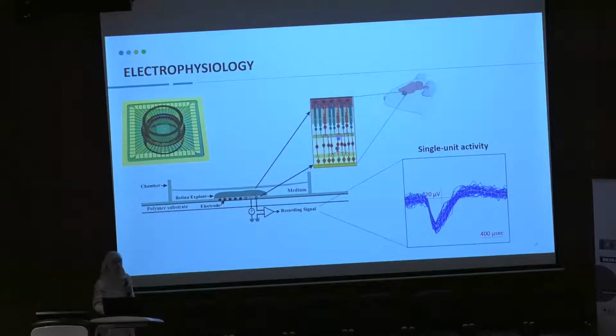To validate our work, we used the printed electrodes to record the electrophysiological activity of the retina from a rat. So we used a multi-channel system. We extracted the retina, and we put it facing the electrodes. And we were successfully able to measure single unit activity from the retina, from the ganglion cells.